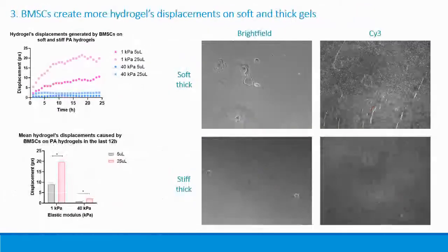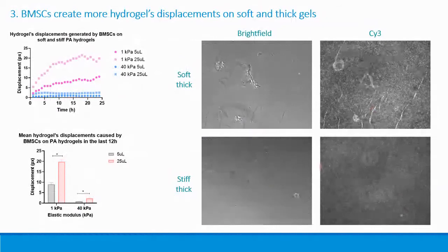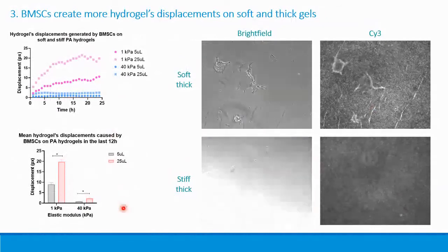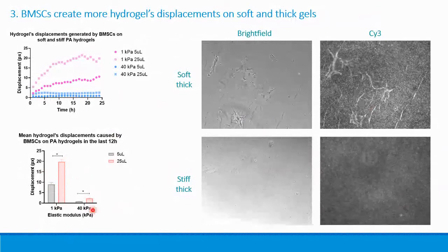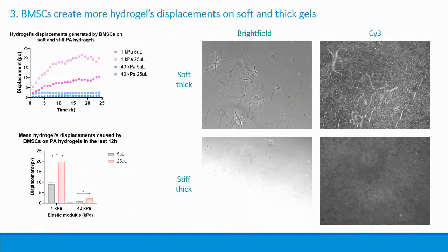We confirmed depth sensing by quantifying hydrogel deformations immediately after seeding. The cells start sensing the mechanical properties and creating hydrogel displacements both on stiff and soft gels, being greater on soft thick gels, as we can see on the video on the channel.